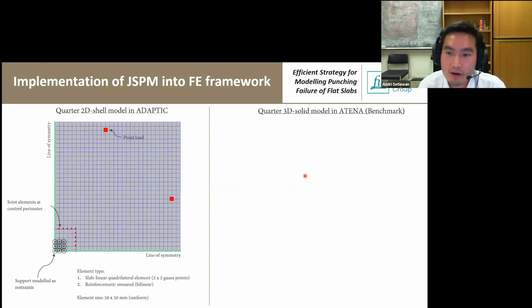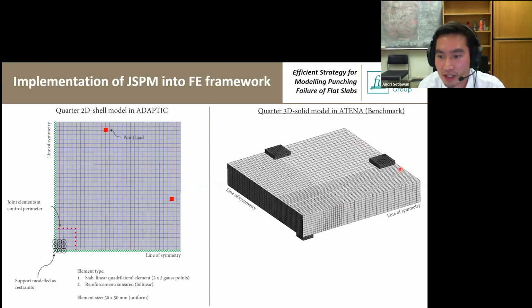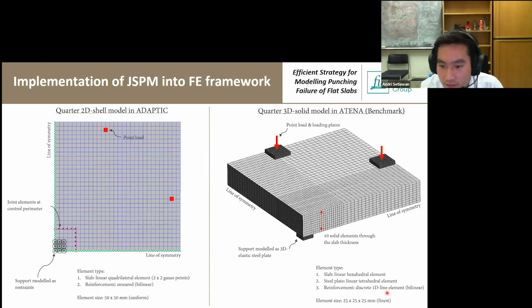For the benchmark, we also did some analysis in a commercial finite element software called ATENA from Cervenka Consulting. This is the same slab model in 3D solid elements. We have the line of symmetry, and the support modeled as a 3D elastic steel plate. We also mesh the slab through the thickness with 10 elements, which gives sufficiently accurate bending behavior, and also the point load and the loading plates. We use linear hexahedral elements, and linear tetrahedral elements for the steel plate. The reinforcement is modeled as 1D truss elements, and the element size is around 25 by 25 by 25 in this region where the shear stress is governing.